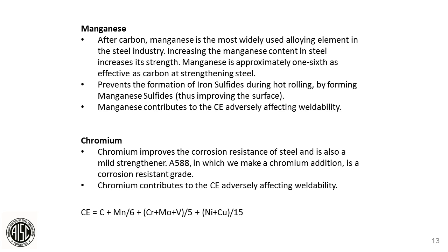Talk about manganese. It's the big hitter right below carbon. After carbon, it's the most widely used alloying element. It increases the toughness of the steel and improves the strength. It typically has approximately a 1/6 effective ratio compared to carbon as far as strengthening. It does have a processing effect of taking care of the sulfur that's in the steel, so it improves the surface of the steel when it's rolled.